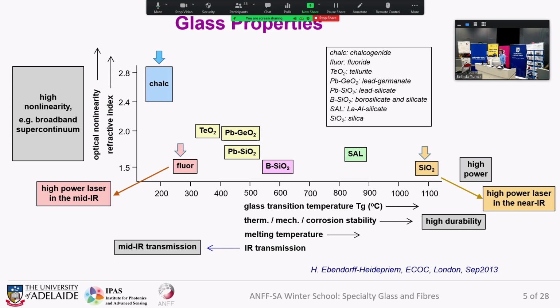The chalcogenide glasses have extremely high refractive index, therefore high optical nonlinearity, and so they are good for so-called nonlinear processing. That means creating new wavelengths, like from one laser, you pump the glass with one laser and you get a broad supercontinuum out of the fiber.